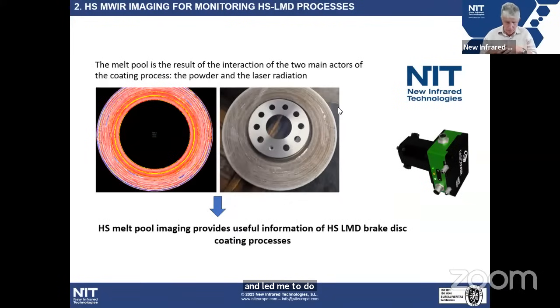As you know, our infrared cameras image the melt pool. The melt pool is basically the result of the interaction of the two main actors in the process, the laser and the powder. We think that imaging the melt pool is one of the best techniques you can use for monitoring a laser-based process. It is very important that the technique you use provides useful information on the process. Otherwise, you are wasting time.